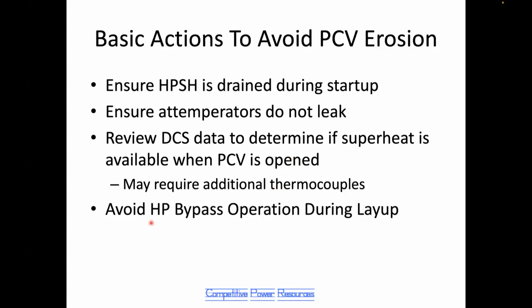One final thought is avoid using the HP bypass when the boiler is not being fired. Not all HRSGs do this, but some HRSGs, if you open the bypass when the gas turbine is not firing in order to depressurize the unit, for example, to expedite and cool it more rapidly, that can cause condensation in the superheater, which will then be pulled through the bypass valve and cause this erosion. So if you're going to depressurize the unit or force cool the unit using the HP bypass, you need to investigate the pipe and steam temperatures upstream of the bypass to ensure that you're not generating condensate and then moving it through the bypass.